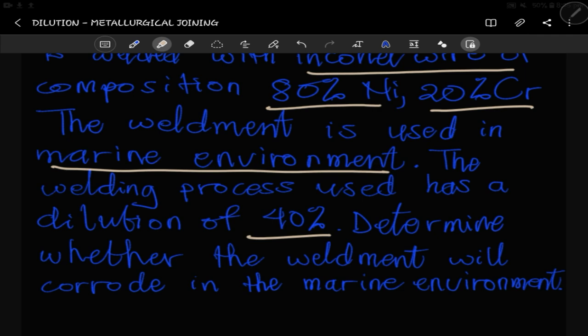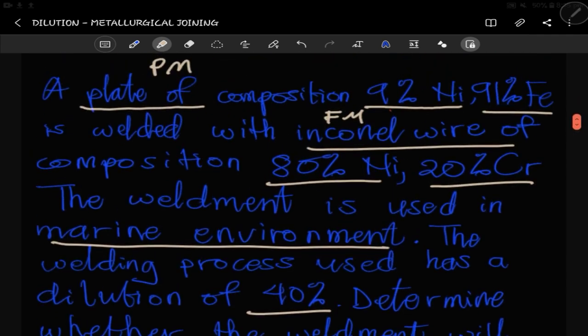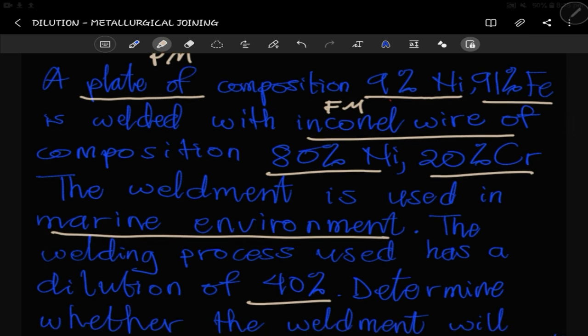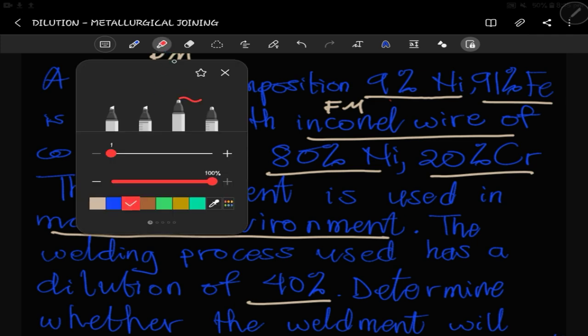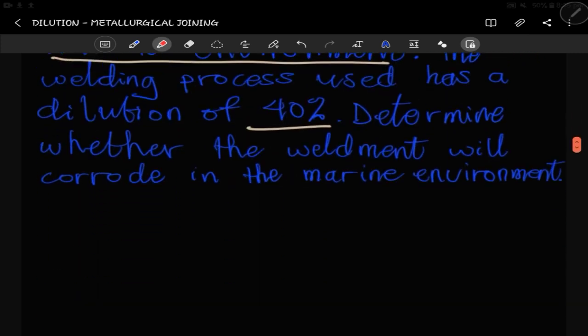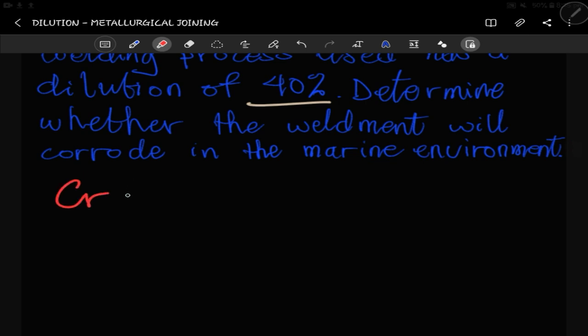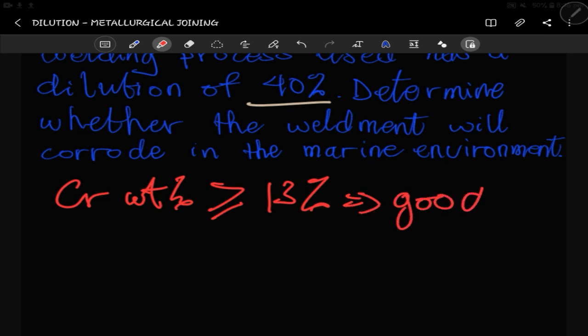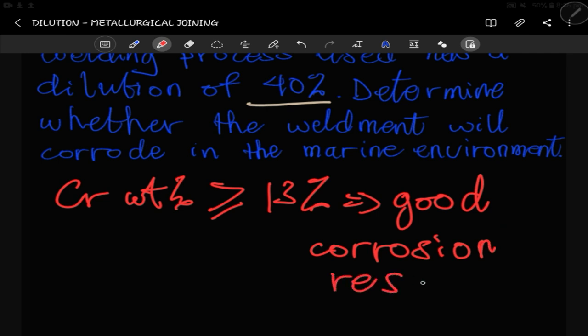We will be able to determine whether it corrodes or not depending on the element that helps the metal develop good corrosion resistance. If you've not done it before, you won't be able to identify the element. But in ferrous metals, the main alloying element that helps the metal develop good corrosion resistance is actually, sorry, not the nickel, it's the chromium. A lot of work has been done on this, and it shows that if the chromium weight percent is greater than or equal to 13%, then it will have good corrosion resistance. But if it is less, then the corrosion resistance won't be good.